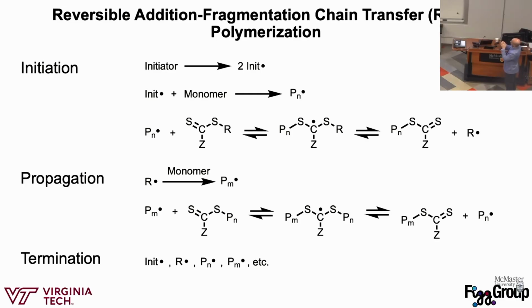After the small molecule RAFT agent is consumed, this PM could just be any sort of growing polymer chain. It can go in solution. We're going to have this thiocarbonyl thio compound on the end of every propagating chain. So this active radical can undergo this chain transfer event, and then it can kick off this PN, and now we get this PN propagating radical.